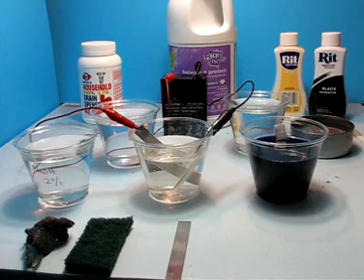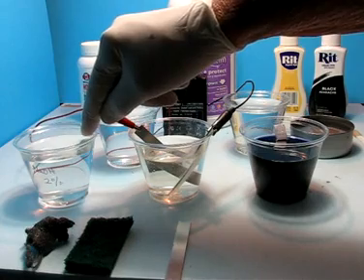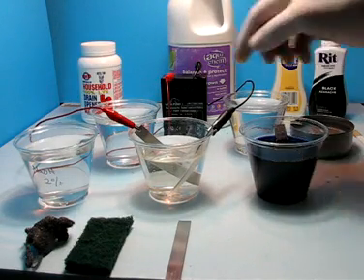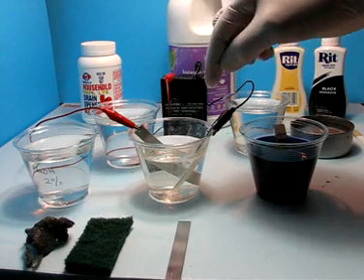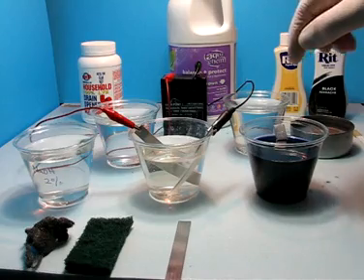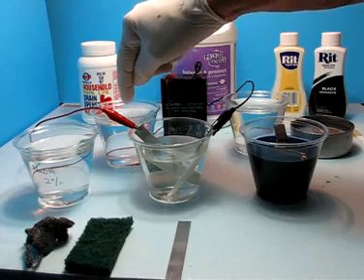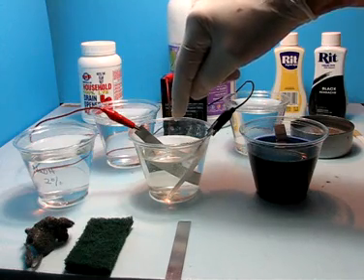At this point there are two options. You can go into a 2% dilute solution of sodium hydroxide, which is household lye, for 1 to 3 minutes — which I recommend — or you can go directly into the anodizing solution, which is the sodium bisulfate. The results are generally a little bit better if you do the sodium hydroxide etch first, and from there it goes into a rinse and then directly into the anodizing solution.